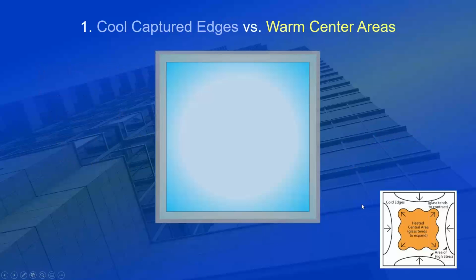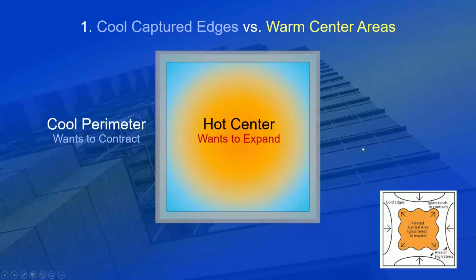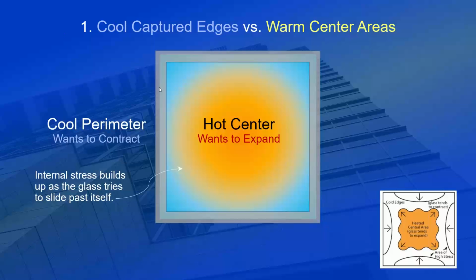So let's look at center of glass for a moment. You've got your glass light, you've got your frame, you've got a warmer center of glass there. And if you're somebody who likes arrows, I appreciate arrows, so I've included that inset image on the bottom right. What can happen is when the glass warms up, the middle of the glass wants to expand because it gets warmer, because of the thermal coefficient causing that glass to expand, but the perimeter stays cool. The perimeter can stay cool because of its proximity to shadows from window mullions or other building elements. It can stay cool because of proximity to the aluminum frame system. For those reasons the perimeter wants to stay cool. But what can happen is you have a buildup of stresses.